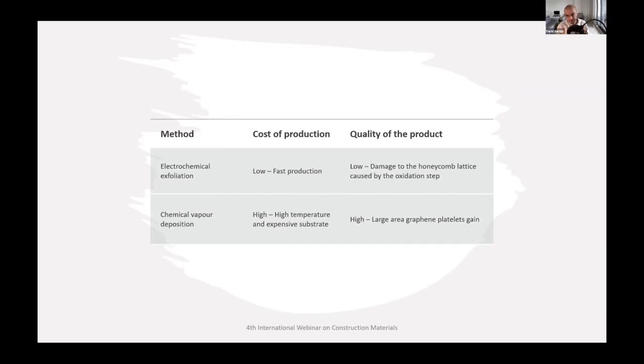Electrochemical exfoliation, the option that we've chosen, refers to the process during which the graphite sheets are oxidized in an electrolyte followed by an ultrasonication. Hydrobromic, hydrochloric, and nitric acid plus sulfuric acids are typically used as electrolytes, from which sulfuric acid is proven to perform in highest efficiency amongst other acids. So we used sulfuric acid for that reason in our studies.